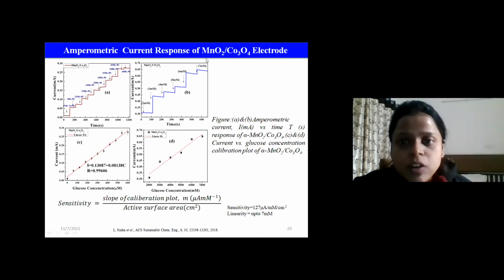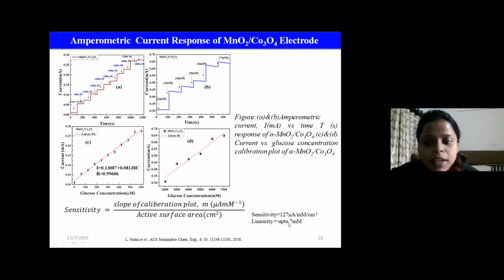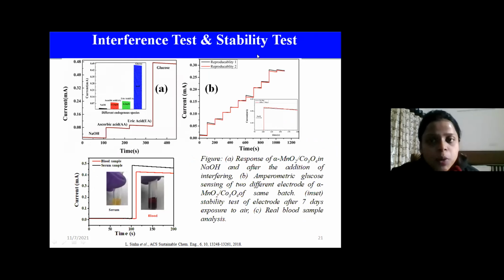Whereas in the case of the hybrid nanomaterial, we can see that the sensitivity has been enhanced to 127 microampere per millimolar per centimeter square, and the linearity has been maintained up to 7 millimolar. So this shows a huge enhancement of the sensitivity and the linearity of the material because of the hybridization, or combination, of two nanostructured materials.